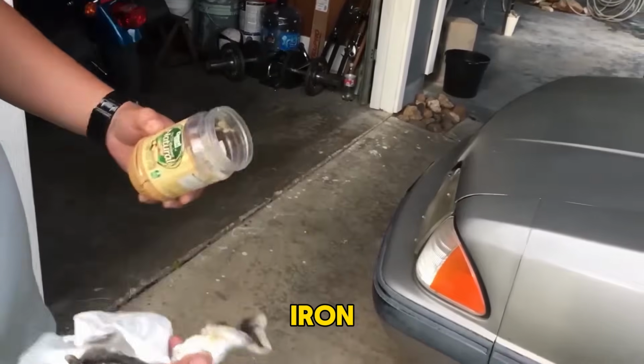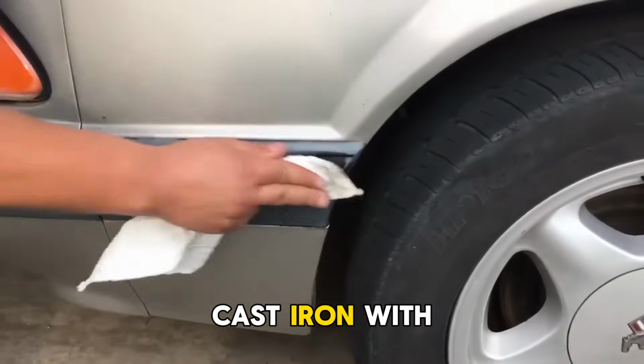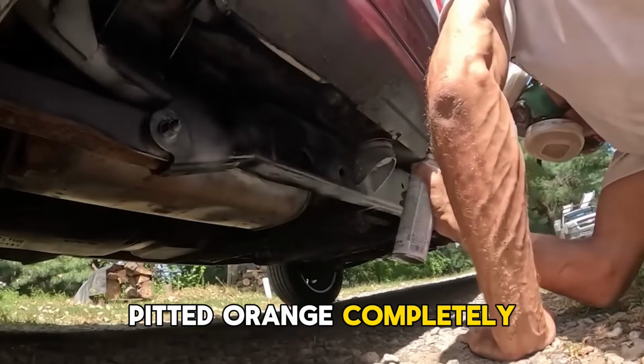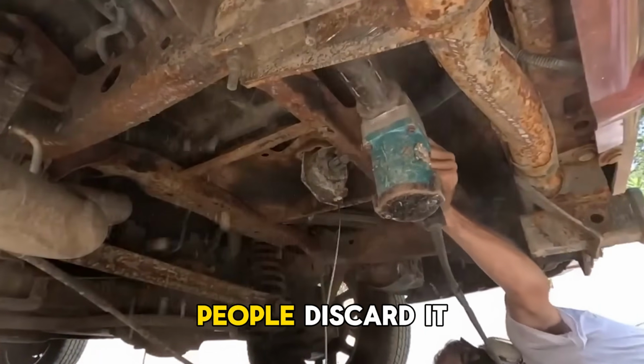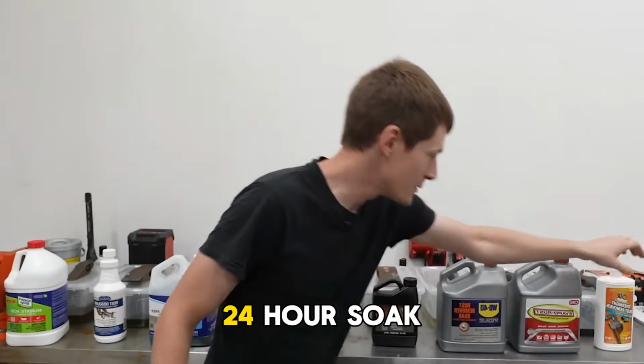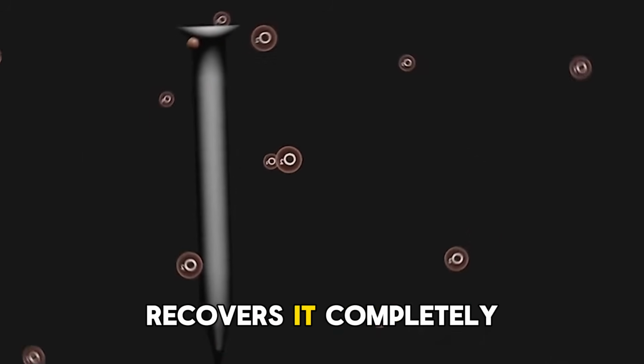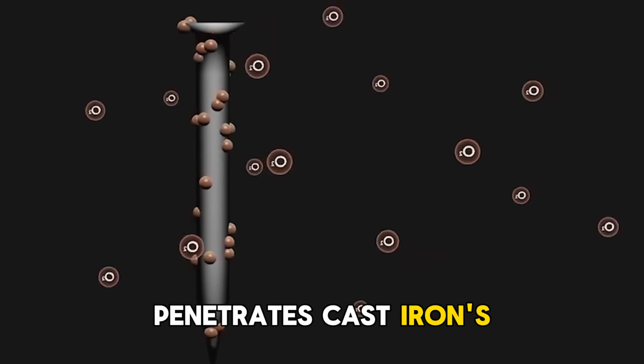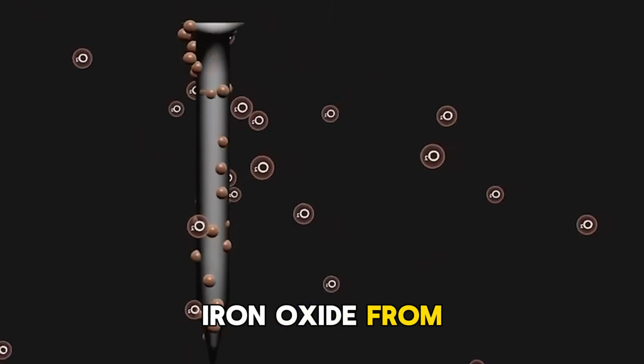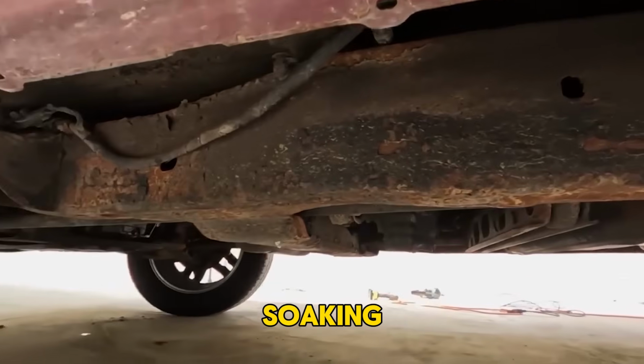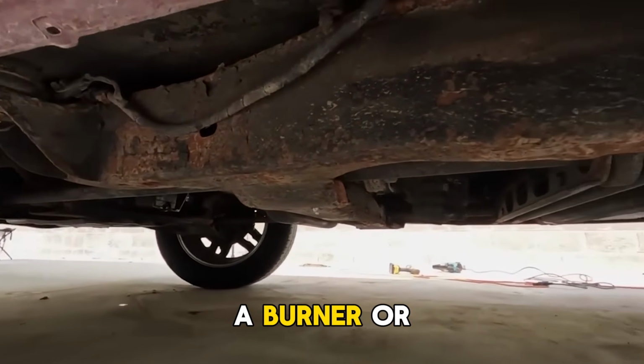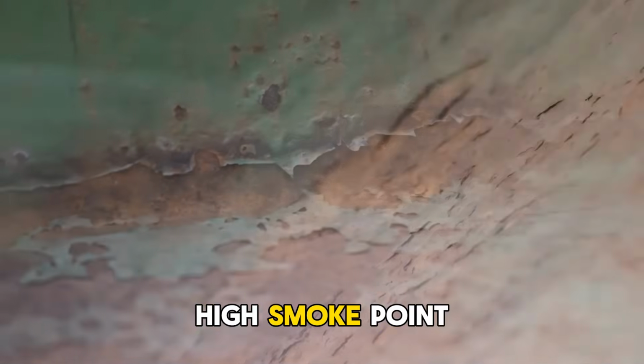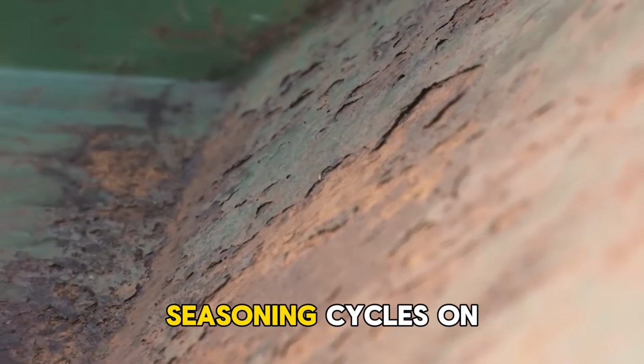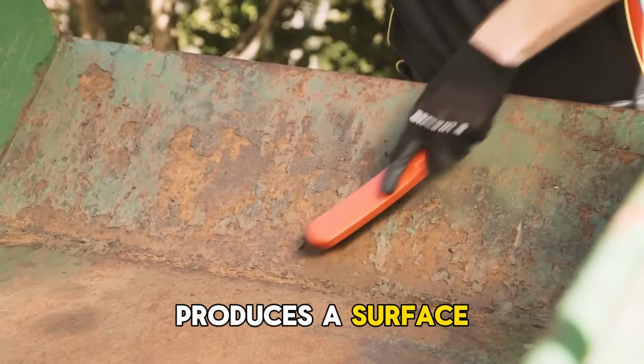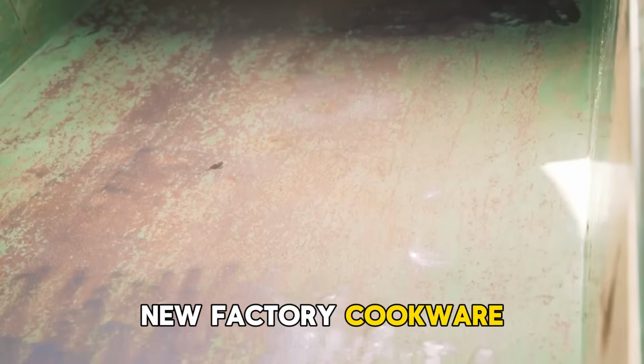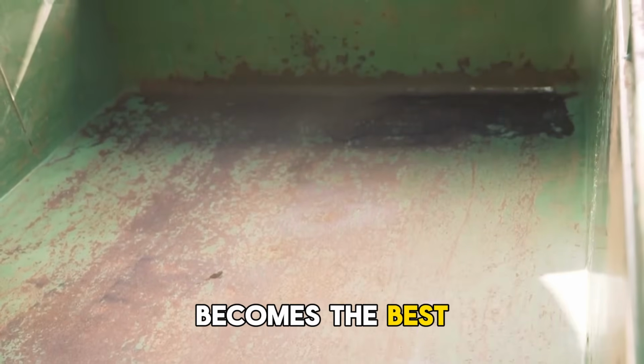Number 9. Cast iron, the most dramatic recovery. Cast iron with severe rust, pitted, orange, completely unseasoned, appears destroyed. Most people discard it. Do not. A 24-hour soak in saturated citric acid recovers it completely. The chelation mechanism penetrates cast iron's porous microstructure and pulls iron oxide from depths no wire brush can reach. After soaking, scrub under running water, dry immediately over a burner or in a hot oven, and season with thin coats of high smoke point oil baked at high temperature. 2 to 3 seasoning cycles on properly stripped cast iron produces a surface equal to or better than new factory cookware. Cast iron you were about to throw away becomes the best pan in the kitchen.